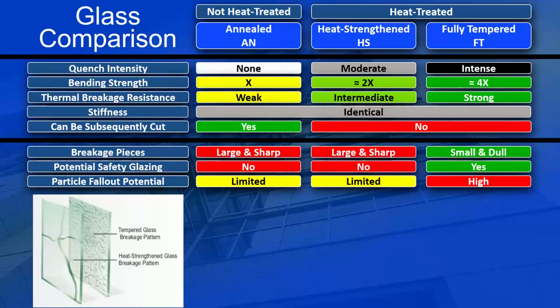Now, as far as safety glass is concerned, the glass doesn't have to be tempered if it is laminated. Safety glass can use annealed plies with a laminate or heat strengthened plies with a laminate.